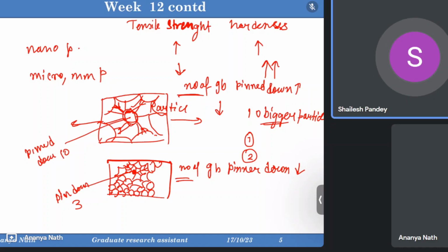And if we are talking about the volume fraction of the particle, like a 20% volume fraction we are adding, is this the volume of the weld zone? Yes. In the weld zone you are adding the powder of the metal matrix composite, right? So in the weld zone, whatever amount of aluminum you are adding, you add 20% silicon carbide. If you are adding 80 gram aluminum, you add 20 gram silicon carbide. So you mix this 80 gram and 20 gram, and then you add that in the matrix.